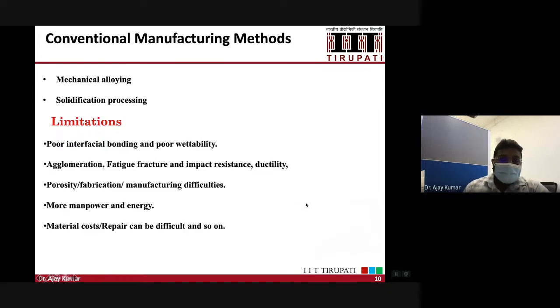As you know, we have mechanical alloying and solidification processing as conventional methods for making composite materials. At the same time, we have limitations. We have poor interfacial bonding and poor wettability between the matrix and reinforcements. We have the problems of agglomeration, fatigue fracture, impact resistance, porosity, and we use more manpower and energy to produce these composite materials using the conventional methods. At the same time, we also face the problem of cost and recycling.